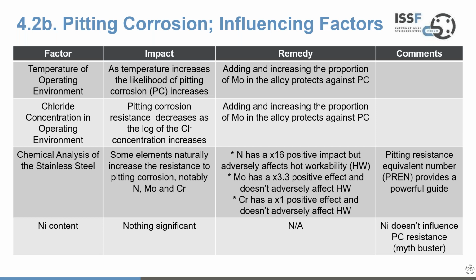And then on top of that, we know that the chemical analysis overall, with three key elements playing an important role. Nitrogen has a strongly positive impact of improving corrosion resistance in this sort of environment, but the downside is you get a worse impact on hot workability, so it's a less easy product to produce. But you don't tend to need nitrogen in huge quantities anyway. Molybdenum has a fairly strong impact, doesn't really affect hot workability, and chromium has a positive impact but not as powerful as molybdenum, and again doesn't adversely affect hot workability. But these three elements together come in an empirical relationship to present what's known as the pitting resistance equivalent number, PREN, which is a very powerful guide to helping choose the appropriate grade of stainless steels when you need to consider this type of corrosion.